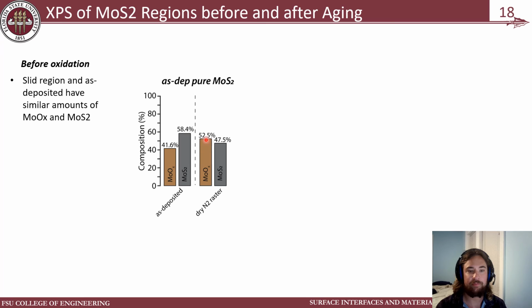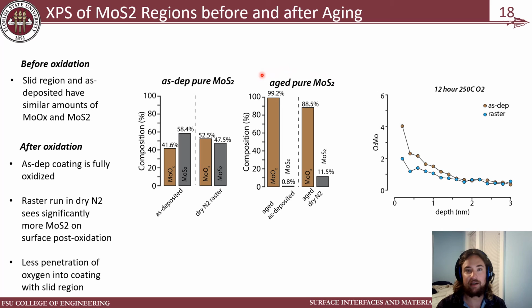Where the big difference occurs is after aging, where in the as deposited coating, the top surface is almost completely moly oxide with very little MoS2, whereas the aged raster region has significantly more MoS2 and less moly oxide. So what we're really seeing here is that after oxidation, the as deposited coating is pretty much fully oxidized, while the raster region run in dry nitrogen sees much more MoS2, which helps us maintain that low coefficient of friction after oxidation. And if we look at